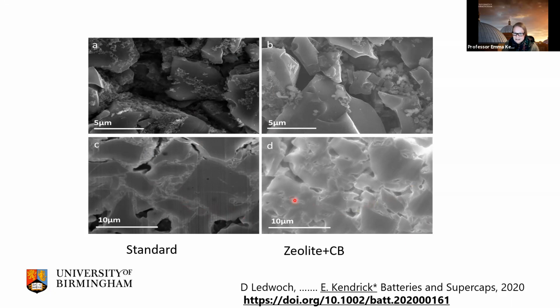With a zeolite additive, we still had small pores in our electrode. So yes, we'd improved the porosity over time of the electrode, but it's not from how we originally thought it was working. And we ended up doing more work this time on using it as an electrolyte additive to show that what was actually happening in here is that we were stabilizing the interface layers over time.